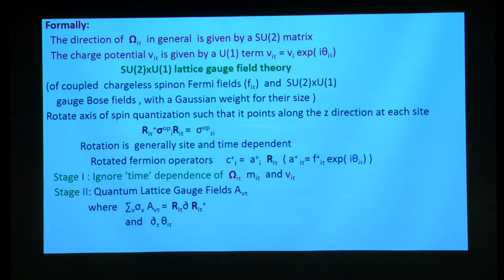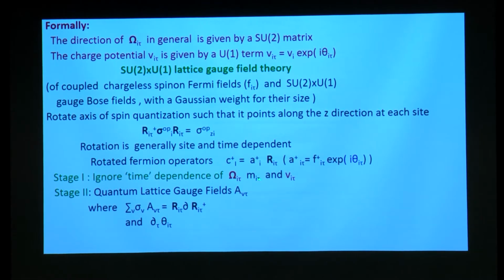Okay, now nothing has happened, but suppose you ignore the time dependence of the charge potential at each site, the magnetic field at each site, and this arbitrary angle. Then I call it stage 1. That describes electrons moving in a static magnetic field directed randomly at each site, and a charge field which is also random at each site, and the weight of these is Gaussian.